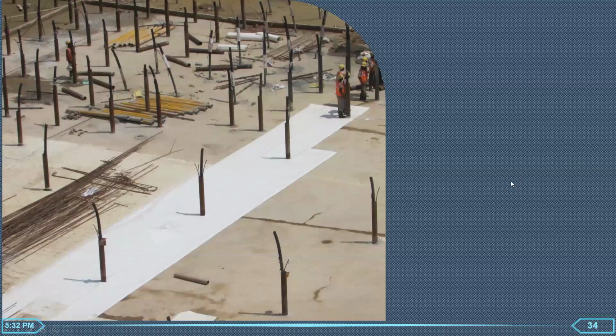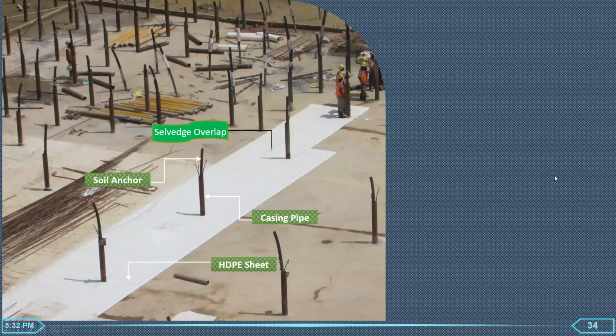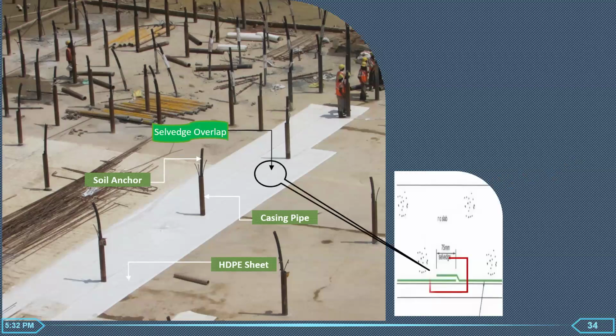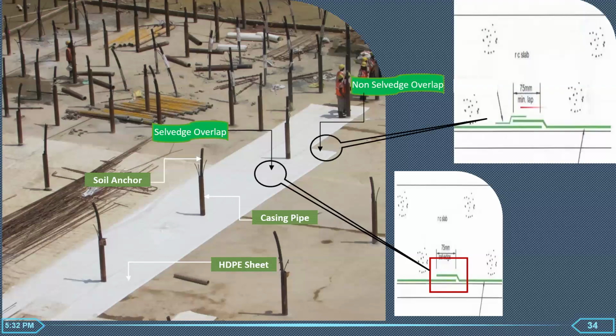This gives all the details of the sheet system, the soil anchor. This is the casing pipe that passes through the thickness of the raft. And this white one is the HDPE sheet. And this longitudinal joint, they call it selvage overlap. It's a very easy overlap. You remove the protective layer, and just press it with a roller, and your joint is ready. You can see how this overlap is made. So just by pressing a roller, this joint is ready. But the cross joint is a non-selvage joint. We had to provide an additional tape to get a proper joint. You can see here, an additional tape is provided at this point.